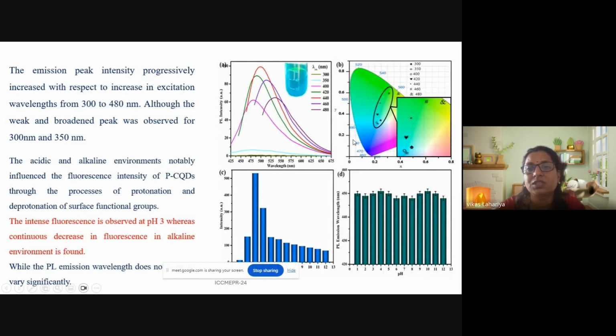This is the emission spectra of the P-doped carbon dot. Under the UV light, we can see with the naked eye a bright blue emission, and from the photoluminescence spectrophotometer, the light emission is around 490 nm, and this is the excitation dependent fluorescence spectra, and the color of the emission is confirmed by the CIE diagram.